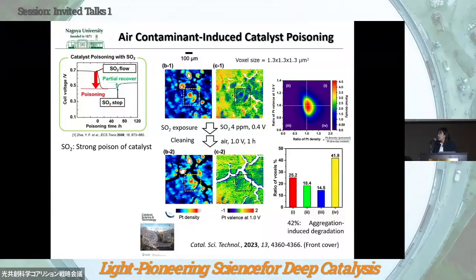By the introduction of SO2 and the subsequent recovery process on the catalyst, we succeeded in performing a statistical analysis of the platinum catalyst degradation in MEA. And we found that the adsorption of sulfur species does not induce a significant structural change in the platinum catalyst. So the simple exposure to the sulfur compounds does not affect the degradation. But the subsequent recovery process promoted the aggregation of platinum, which leads to the loss of the catalytic activity.